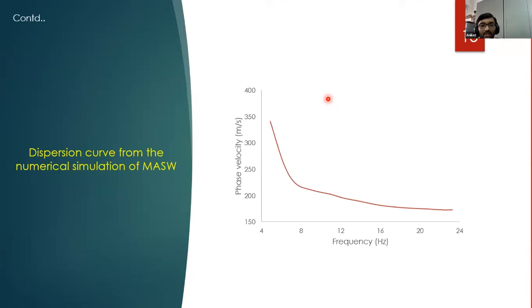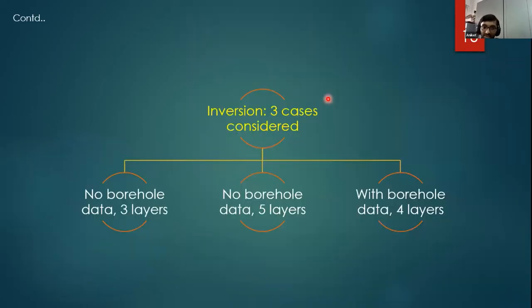After applying the loading, recording the signals, and doing the processing, as in step 2, this is the final dispersion curve that we obtain. But now comes the most important part of our work. The next step is the inversion and generation of the VS profile. What we are interested to know is what will be the difference in the results when the inversion is carried out without any borehole information and with the borehole information. So we considered 3 cases.